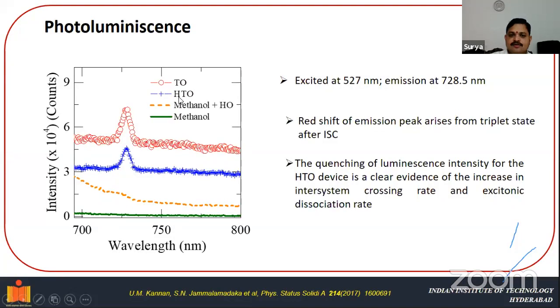As we added holmium to the titanium dioxide, the photoluminescence decreases. What does it mean? If the photoluminescence is more, that means a greater number of electron-hole pairs will recombine. Since the photoluminescence decreases, that means fewer electrons and holes are recombining. That means more charge transport within the device.